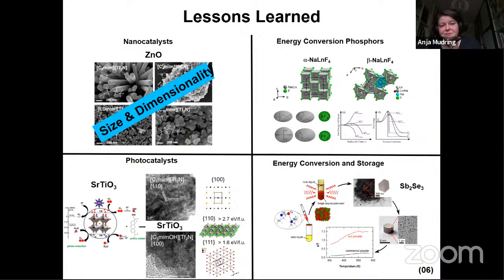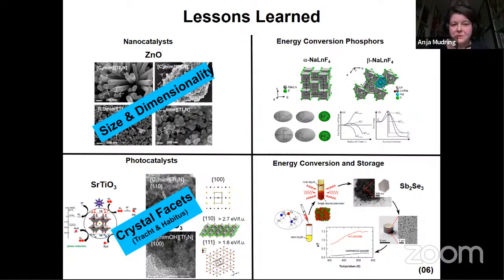And here ionic liquids are really smart materials because they attach to the surface. So depending on what kind of ionic liquid you use and what the interactions look like, you get one of the facets preferentially expressed. That's a big plus of ionic liquids in the synthesis.